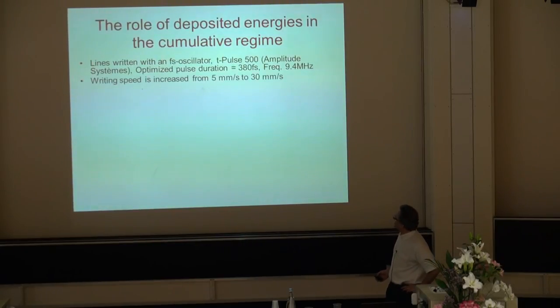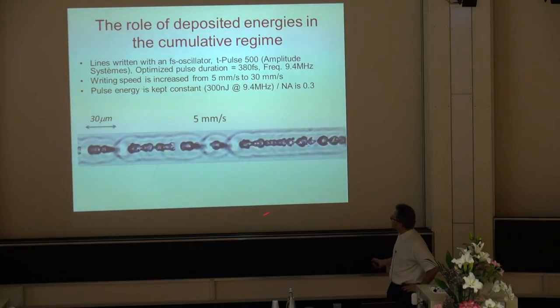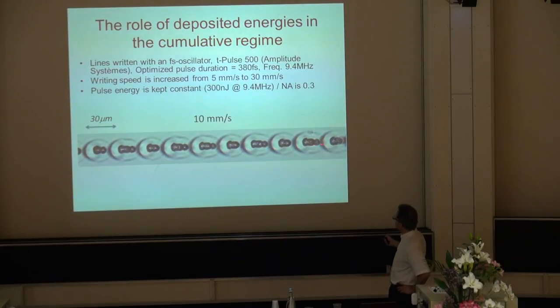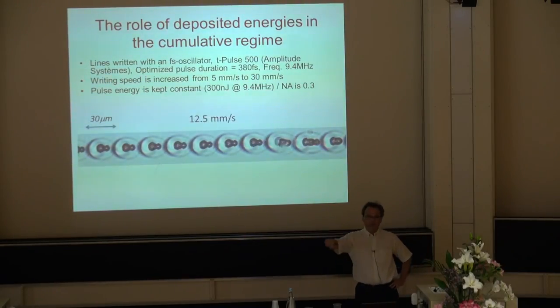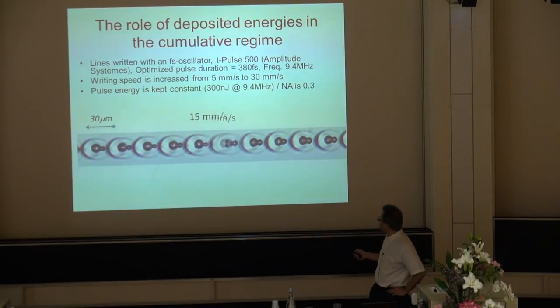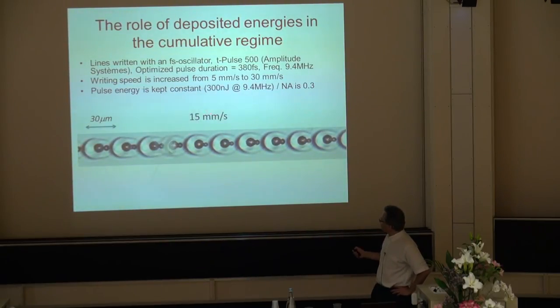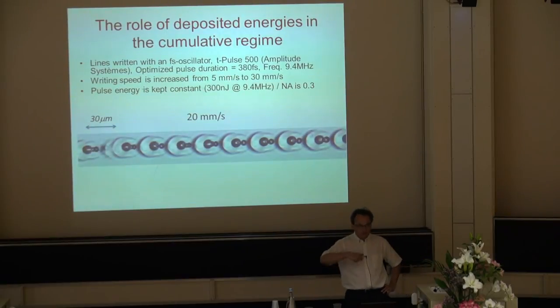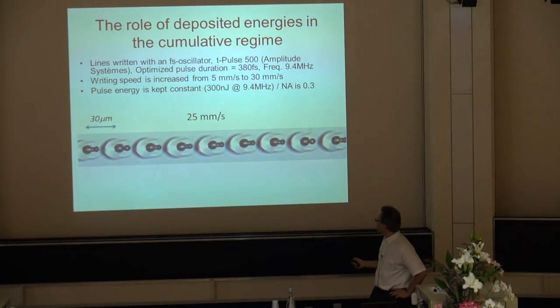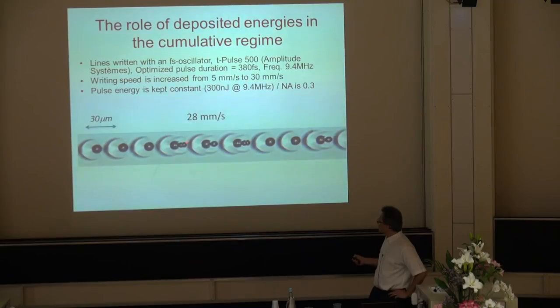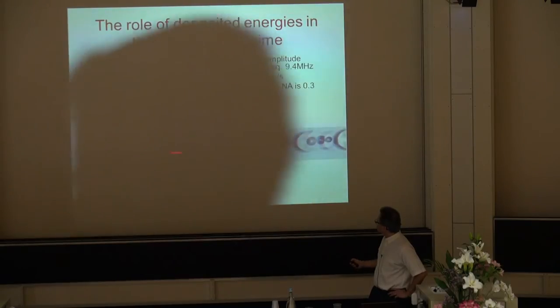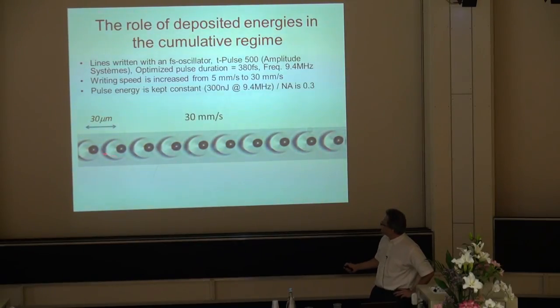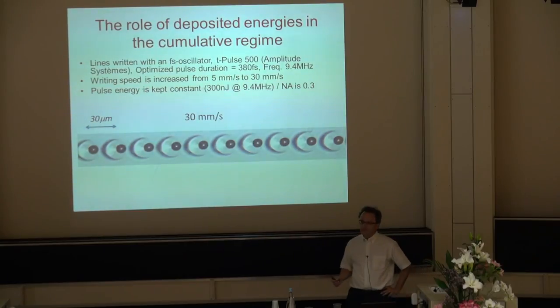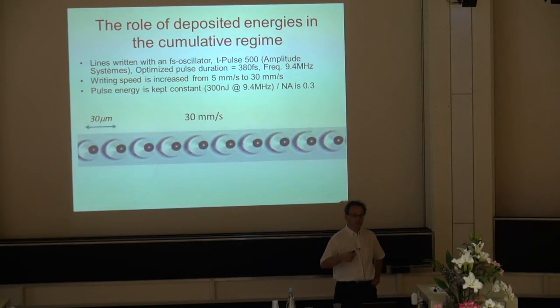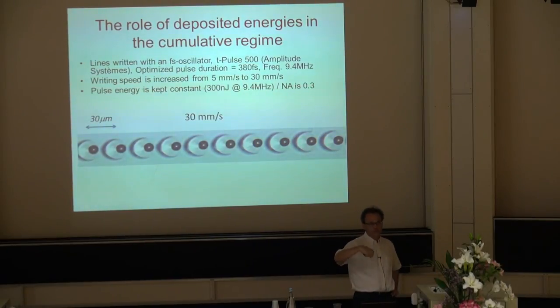Now, when you explore that, an interesting phenomenon occurs. You literally boil the glass. You see here, we are writing lines, and then you see some bubbles forming. But the interesting thing is when I keep on accelerating how fast I write, eventually I get to a point where the structure self-organizes and eventually becomes perfect. And the periodicity of those structures is driven by the physics, not at all by the laser. I'm not stopping the laser, okay?